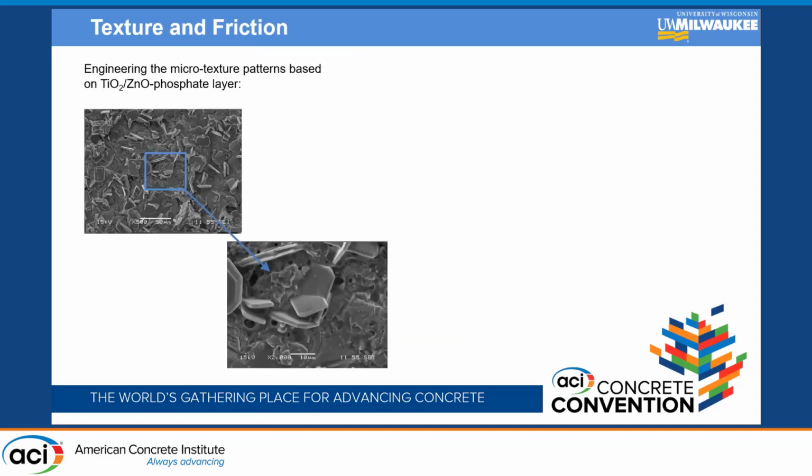So moving forward, this is the texture that we obtained on this ceramic layer, and we were able to impose a crystal structure at the surface, with crystals spaced between themselves. The crystal size, as you can see here, is more or less 10 to 15 microns, which corresponds to the micrograph of the lotus leaf that I presented at the very beginning of this presentation. So we have this lotus leaf-like structure. Of course, it does not look the same, but it serves the same role.